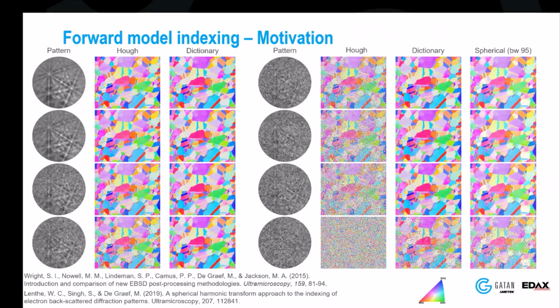And this is again stuff I find truly mind-boggling. In the 10 years I've been with EDAX, this pattern here that I'm looking at has enough information to get basically perfect EBSD data out of it. So again, we always want to get the best patterns we can, but oftentimes we're controlled by what our sample is. So we can get these low quality patterns and turn them into perfect data sets. And again, that's just mind-boggling to me.